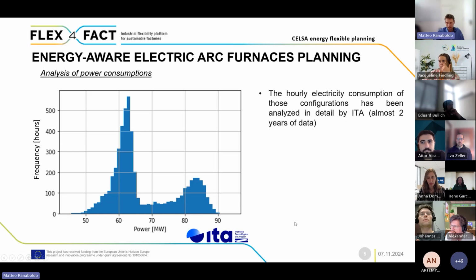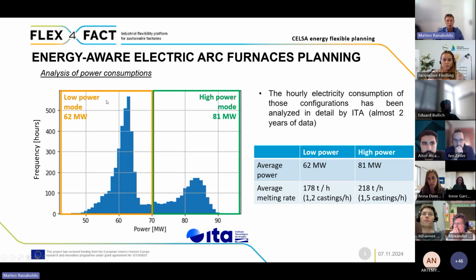And this is part of a study that was done by our colleagues from ITA, the Technical Institute of Aragon. They analyzed the consumption of almost 2 years of data. And what we see here is the hourly average electric consumption in each of these hours for the two furnaces. So if we mix this with knowing the power mode that was used in each moment, it was clearly visible that there are these two modes, the low power mode and the high power mode. And it has been possible then to characterize the average consumption of both of those configurations.